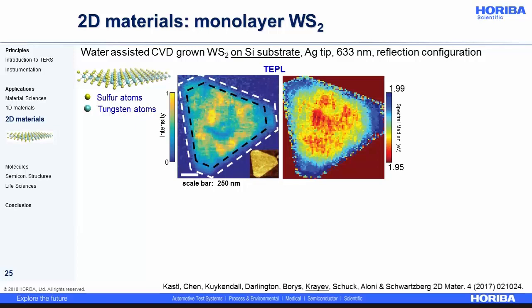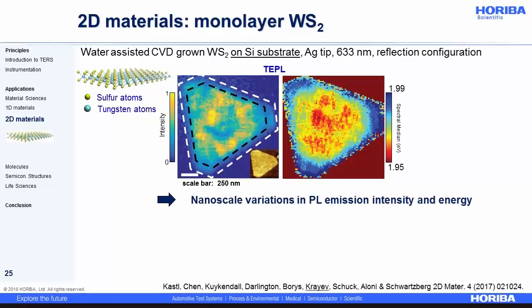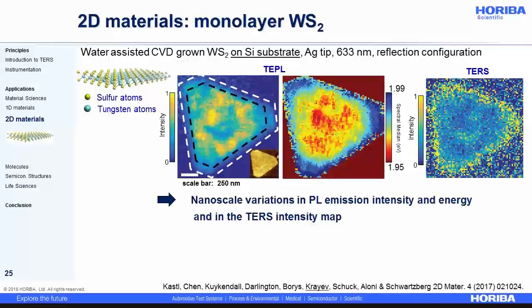Another example with tip-enhanced photoluminescence and TERS characterization of monolayer tungsten disulfide crystallites grown with water-assisted CVD. On the left, the nano-PL intensity, and on the right, the nano-PL spectral energy. As a first observation, within the interior region of the WS2 flake, the nanoscale PL exhibits spatial variation in intensity and in energy that are not correlated with the topography image that you can see very small in the inset. The same behavior is observed with the TERS intensity map, with more Raman scattering within the edge region.